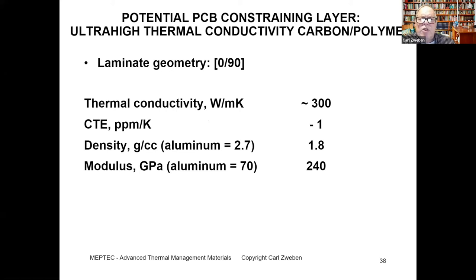So here's one possible constraining layer, which consists of ultra high thermal conductivity carbon fibers in a polymer like epoxy. The laminate geometry with the fibers oriented at 0, 90 degrees will have an in-plane thermal conductivity in the range of 300 watts per meter Kelvin, and an in-plane coefficient of thermal expansion of -1. And that combined with the high modulus, which is actually much higher than aluminum, provides the constraint. And we also notice it has a much lower density than aluminum and certainly much lower than copper Invar copper.